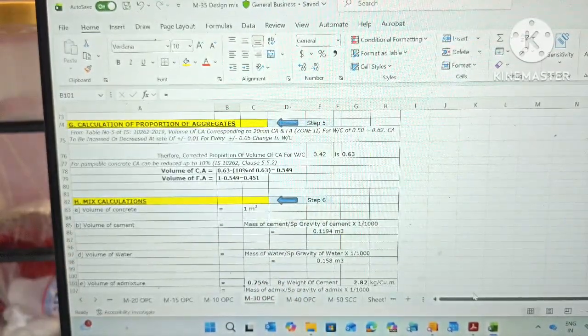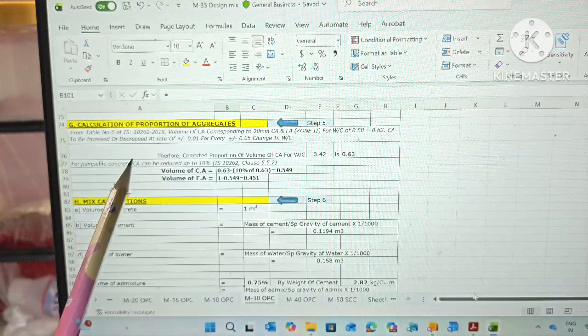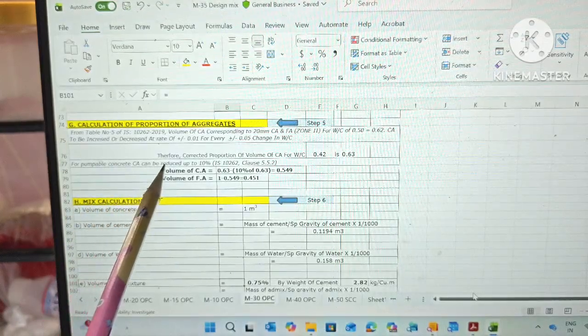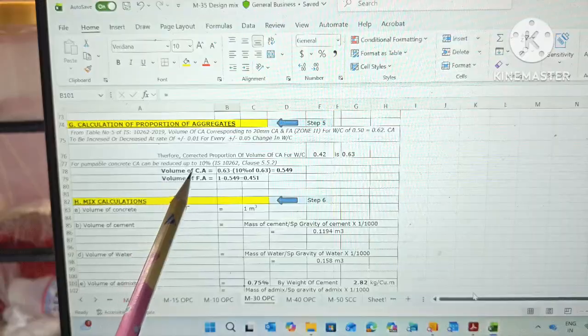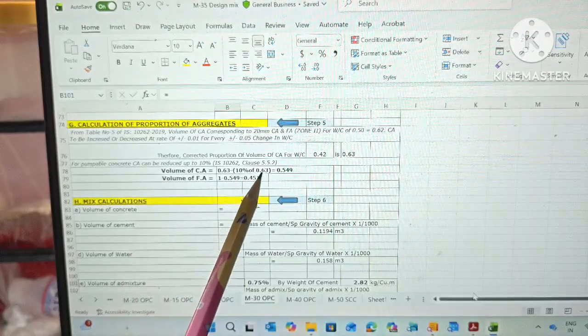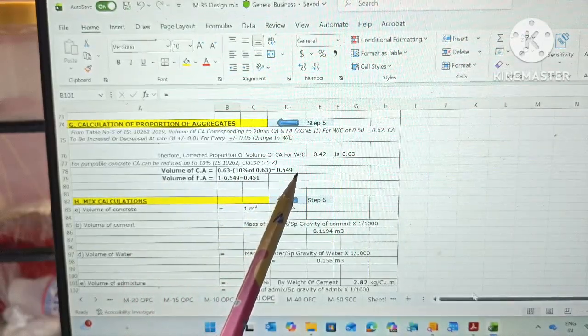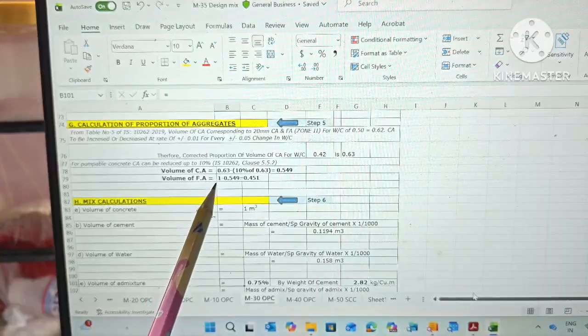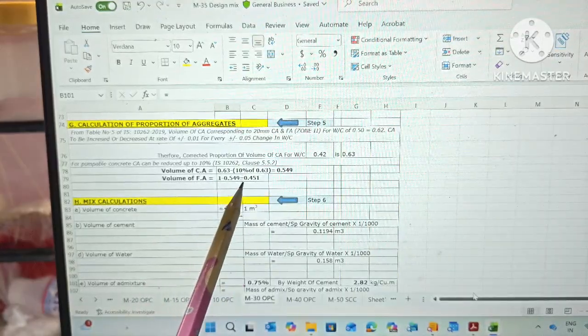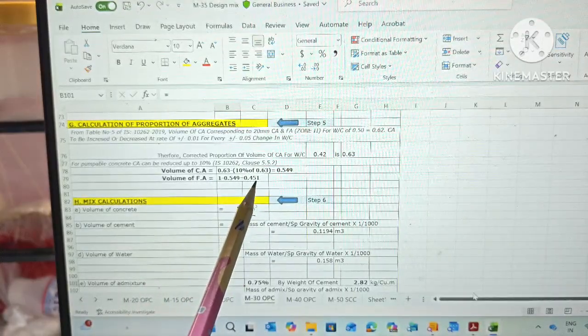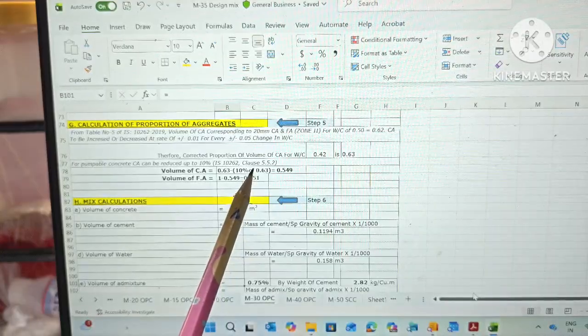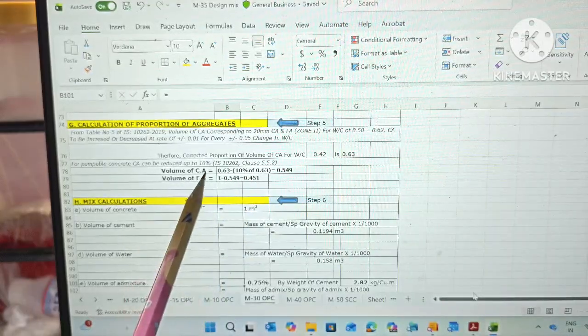Friends, since the concrete is pumpable concrete, coarse aggregate can be reduced by 10%. So volume of coarse aggregate will be 0.63 minus 10% of 0.63, that is 0.549. Now volume of fine aggregate will be 1 minus volume of coarse aggregate, that is 1 minus 0.549, which is equal to 0.451. So here we complete the calculation of proportion of aggregates, that is volume of coarse aggregate and volume of fine aggregate.